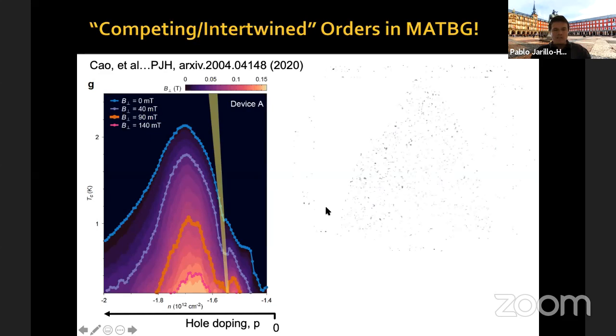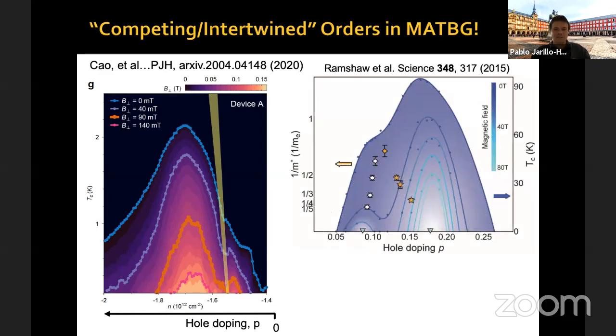And this again is quite reminiscent of some of the behavior which is observed in the cuprates, except that in the cuprates you have to apply up to 80 tesla or more to split the overall superconducting dome into 2 superconducting domes. And of course, another difference is that we can take these measurements continuously. These are continuous data point measurements, whereas this involves making different crystals, and in some cases different material classes, in order to populate this diagram. So let me leave this, and I'll come back to this phenomenology a little bit later.